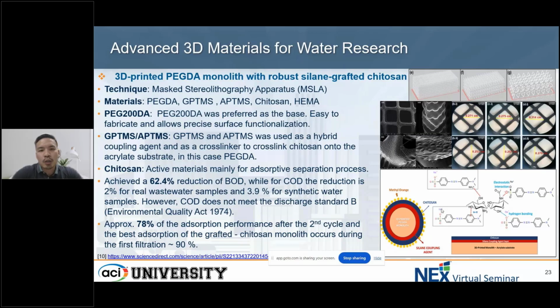Chitosan is a polymer that is quite a well-established material, but there is very recent research on coating chitosan on the PECDA itself. We coated the chitosan on the PECDA and used it for textile wastewater treatment, taking samples from industry. We found that this chitosan with the 3D printed monolith gave a very good BOD reduction of 62.4%, while the COD reduction for the real wastewater treatment was only 2%.